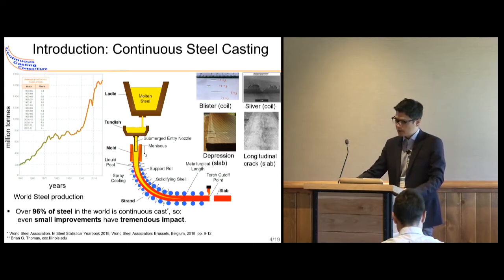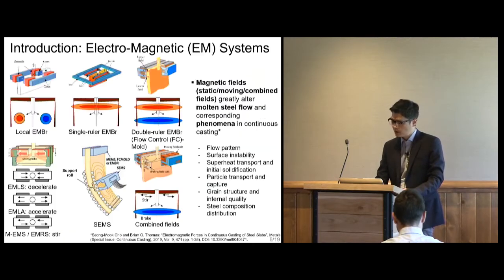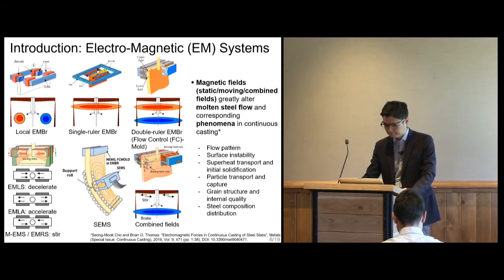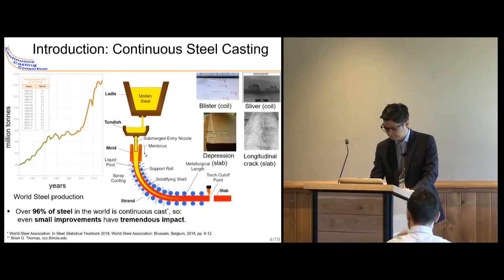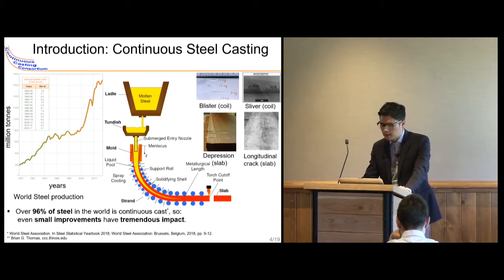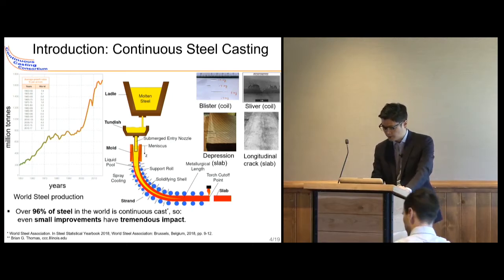And in the mold region, there are complex multiphysics phenomena, and if these phenomena are not controlled properly, they can cause many defect formations such as gas bubble defects, non-metallic inclusion defects, depressions, and crack formations.